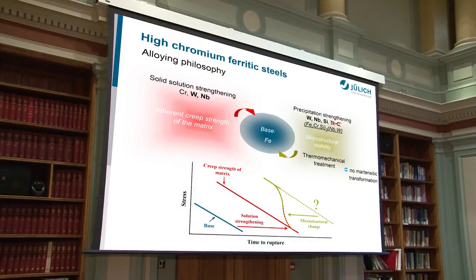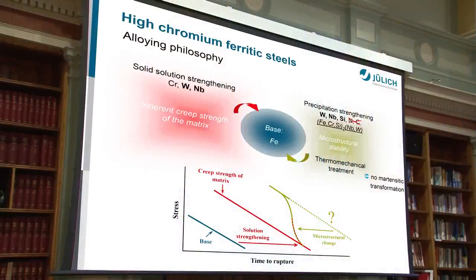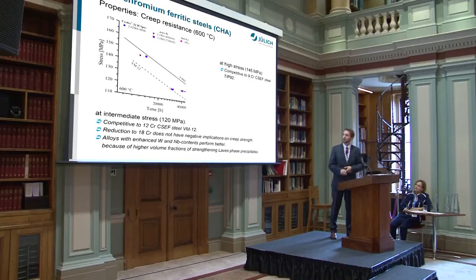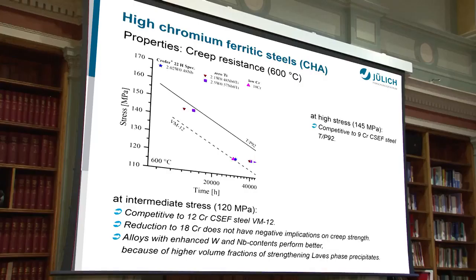Bernd's presentation continued to describe how, by optimizing the balance between tungsten and niobium in ferritic stainless steels with around 17 to 20% chromium, creep strength could be maintained or improved. Niobium enables this by increasing the volume fraction of Laves phase and by refining particle size and thermal stability. Through this development route, the award-winning authors have demonstrated that creep and steam oxidation resistance at 600 degrees centigrade and above are much superior to 9 or 12% chromium ferritic steels, and in the case of steam oxidation, resistance is of the same order as that available from much more expensive high chromium austenitic stainless steels.